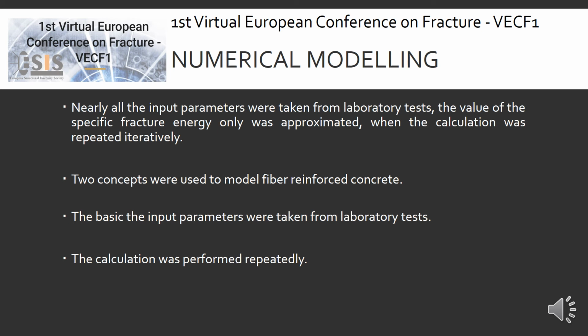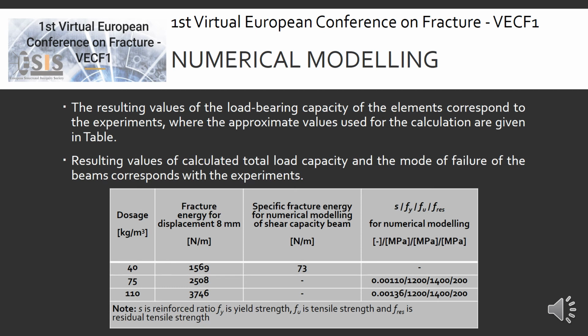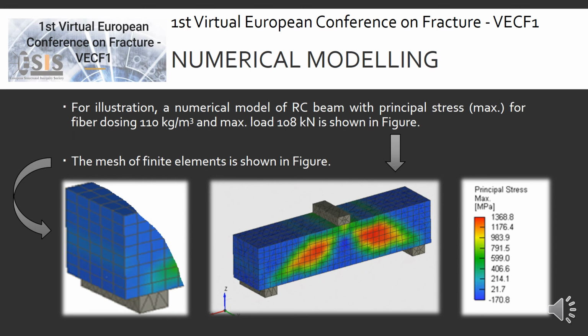The input parameters were taken from laboratory tests. The calculations were performed repeatedly. The resulting values of the load-bearing capacity of the elements corresponded to the experiments, where the approximated values used for the calculation are given in the table. The resulting values of calculated total load capacity and the mode of failure of the beams corresponded with the experiment. For illustration, a numerical model of reinforced concrete beams with maximal principal stress for fiber dosage 110 kg per cubic meter and maximal load 108 kN is shown in the figure. The mesh of finite elements is shown in the figure.